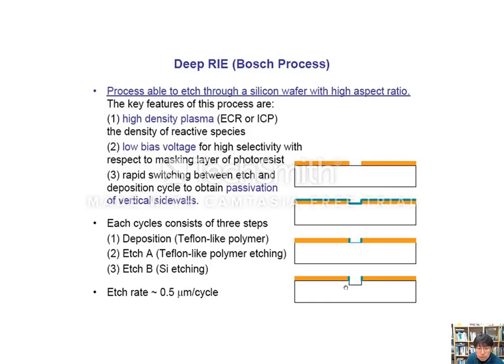Okay, so let's talk about this a little bit more. This is like a cyclic process. You put the Teflon-like polymer deposition first, and then you etch it, etch A, and then etch B is the silicon etch. So you have a kind of double protection, and then you etch A for the polymer, and then you have the silicon etch second. And then what is the next step? You apply this green layer again, and then protect the sidewall, and then you etch the silicon again. You repeat this cycle over and over again.